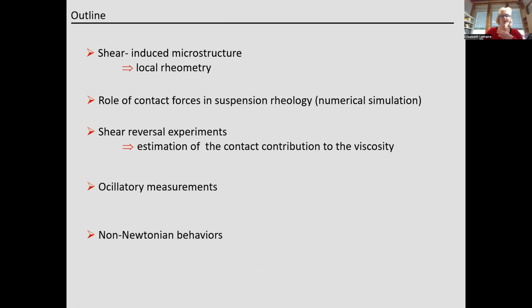So now I've finished my introduction, and I'm going to review some features of non-Brownian suspensions. So the first thing I would like to talk about is the shear-induced microstructure, and I would like to comment on the consequences of the athermal characteristic of non-Brownian suspensions. Because if the particles are athermal, that means that the suspensions, the non-Brownian suspensions, are always out of equilibrium, and their structure is controlled by the flow. So for non-Brownian suspensions, we have a strong coupling between the flow, the microstructure, and the rheology.